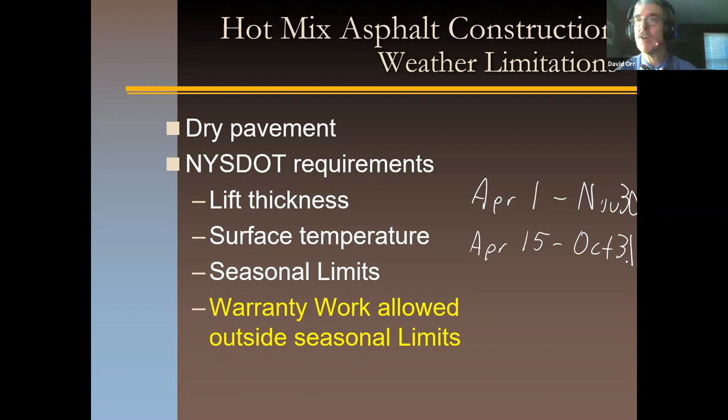But truth be told, what they found is when they've gone back and looked at warranty work, even with a warranty, a couple of years later, half or more of the jobs have problems because they couldn't get the density. It didn't really do what they wanted it to do. It gets too cold at night, it doesn't actually get the density, it doesn't bond, it doesn't hold up as well as it should. So you really want to stay closer to the center.